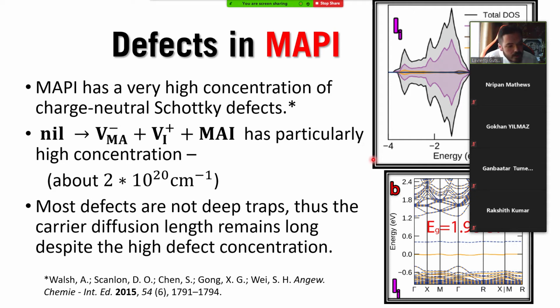But the reason these are not a problem still is because when you do molecular dynamics calculations, you'll see that they start to fade in and out. This material is very plastic, and basically the way you can explain this is the electron-phonon coupling allows the carriers to escape these traps. So these traps exist, but they don't exist constantly. The fact that the material is so plastic actually removes them as they move. So the plasticity is a very important part of the defect tolerance of this material.